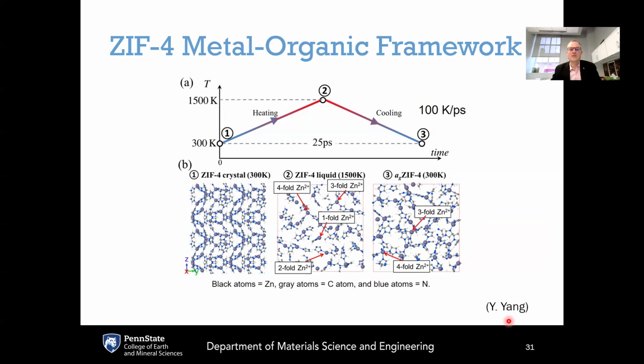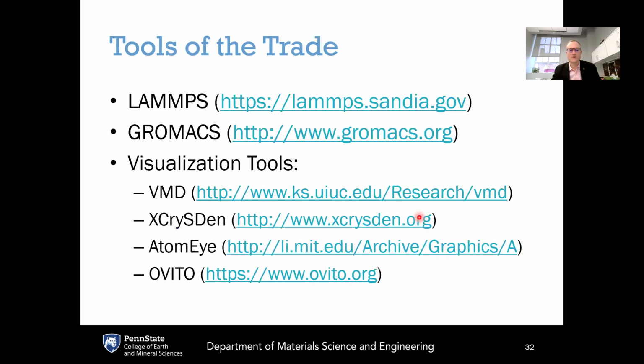He did simulations using ReaxFF, using Adri van Duin's reactive potentials, that show how this metal organic framework called ZIF-4, which is a zeolitic imidazolate framework, behaves. It is a metal organic system, so it's a combination of different types of bonding in that as well. Starting off with a crystal here, and then heating it up into the liquid state, and then quenching it down into the glassy state. And you can get the atomic level details here of what the crystal looks like, what the liquid looks like, and what the glassy state looks like.